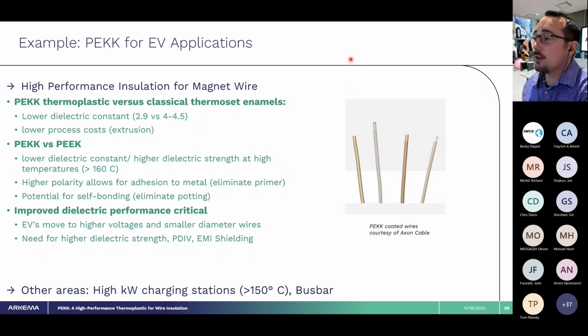Versus classic thermoset enamels, we've got a much lower dielectric constant, especially at temperature, as we've shown. Also, you'd be moving to an extrusion process, so you can remove some of the cost of solvent processing from the traditional enamel coating. This makes sense as motors look to densify, which will drive potential voltages higher, and of course operational temperatures higher, to 180 to 220 degrees C.